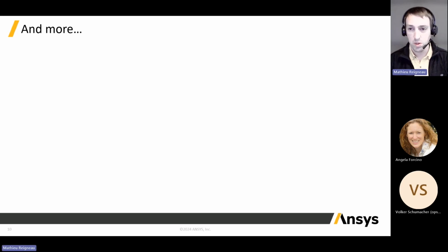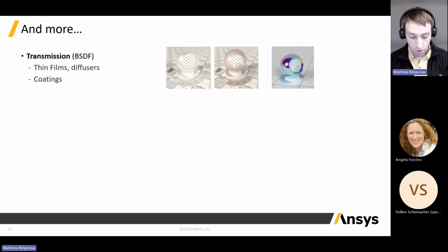Many aspects of BRDF can be captured and restituted and obtained through simulation. Considering not just reflection, but also the transmission. So BRDF, the R stands for reflection, but transmission can occur. And when we capture both reflection and transmission, we call it a BSDF. We generally do this kind of capture for thin film and diffuser or coatings, if you need to blur out some lighting or have a certain coating to split colors on a surface.